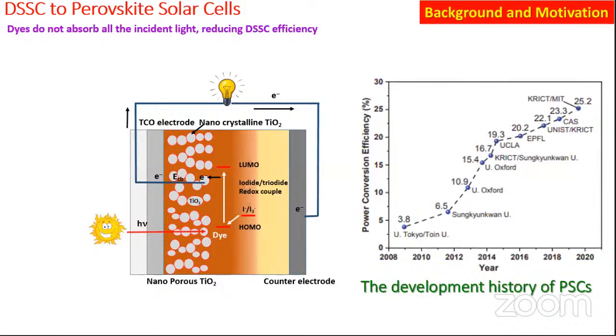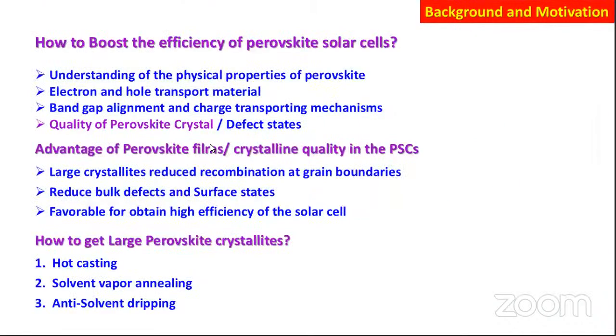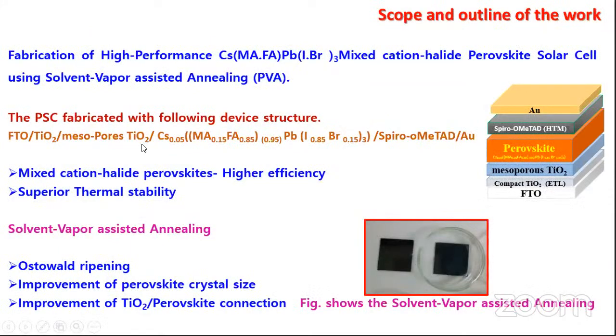Ma'am, this SVA method was already done on other perovskites, but in my case, optimizing the molar ratio and the thickness of the two layers is more important. Generally, this kind of high efficiency perovskite solar cell is made in a glove box, but I made this device in ambient air, in a 20% humidity controlled room. This one is the main reason. Further, along with this we are increasing the crystallinity and get some more efficiency, but this one is the major thing. Mixed cation with the optimized condition, this molar ratio is very important. This solvent vapor annealing is an already existing one, I just applied it, but this is the main thing.